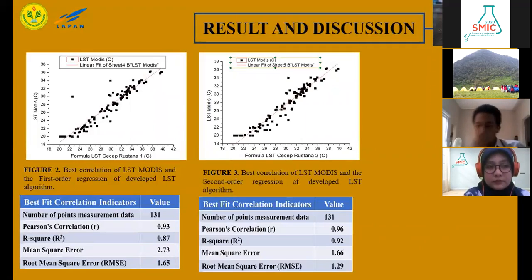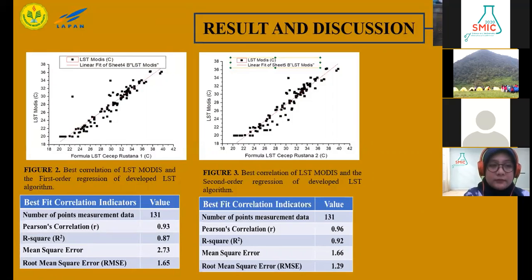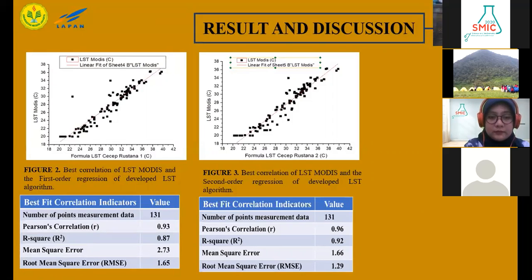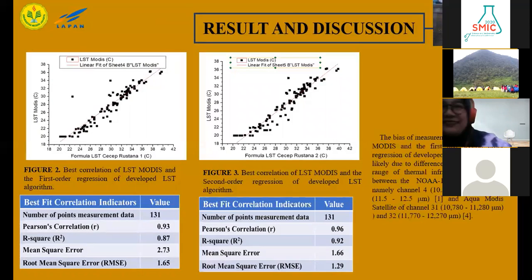The third figure is the best correlation of LST MODIS and the second order regression of developed LST algorithm. In below is the best fit correlation indicators has 131 points measurement data with root mean square errors of about 1.29 and R squares of about 0.92.